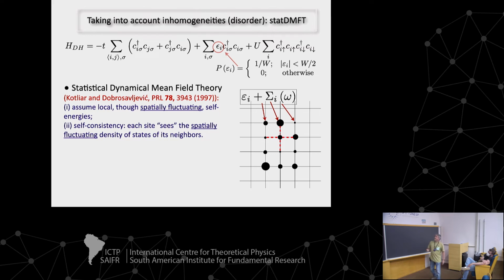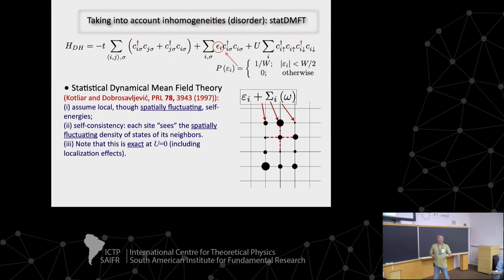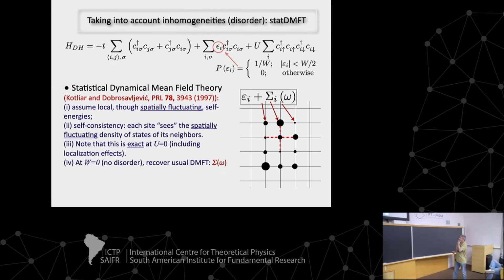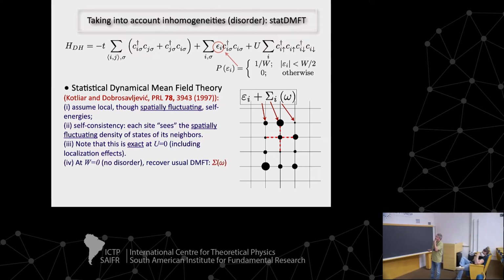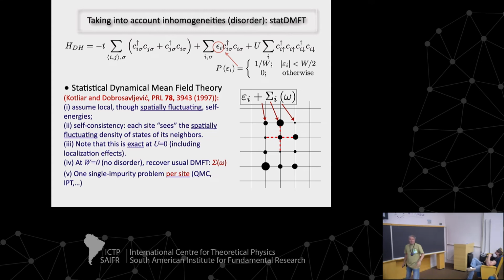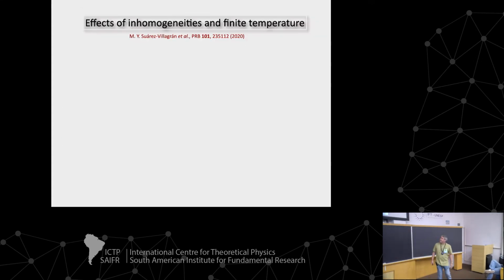So this was the nightmare of my student. The theory is exact at U equal to 0. It's a non-interacting problem, a disordered non-interacting problem. That includes, if you are careful to solve it, even localization effects. With no disorder, you recover dynamical mean field theory. And as I said, one single impurity problem per site that you can solve with some technique.